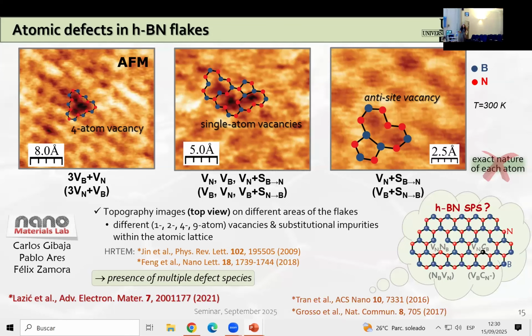Using only atomic force microscopy, it is difficult to actually know the exact nature of each of these atoms. One has to combine it with high-resolution transmission electron microscopy. And if we compare our results to those published by other authors who also observe, with high-resolution TEM, similar or the same defect structures, we basically come to the conclusion that what we have in our hBN flakes are multiple defect species. Now, we still don't know which exact defect is optically active. That is still an open question in the community, and it's quite important to know that so that we can deterministically produce those defects that are producing single photon emitters.